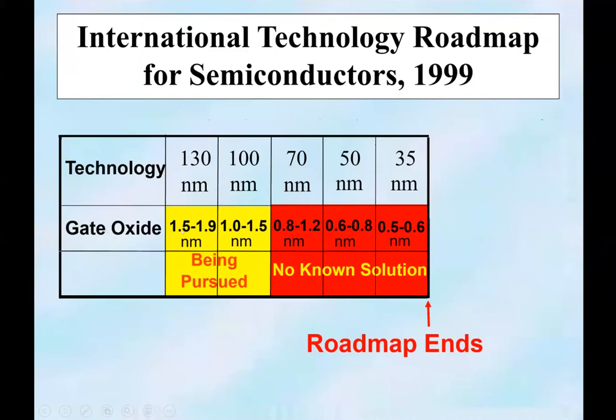I highlight this because the group also highlighted this item as the one that cannot be scaled much further. So 130 nanometer is being pursued. 70 nanometer is going to need oxide thickness of about 1 nanometer, and 50 nanometer technology less than 1 nanometer. 35 needs to be about half a nanometer of oxide thickness in order to control the leakage current, the off-state current, to turn off the short channel transistor. And after that, it doesn't think it can be done. There's no solution. That's the end of the roadmap. That's what the committee says.